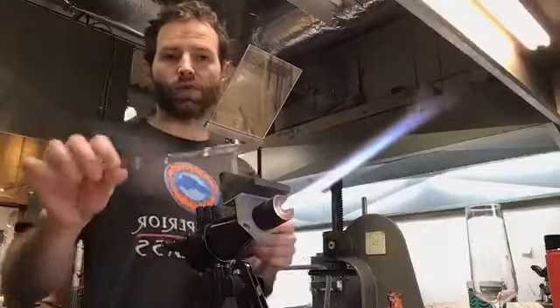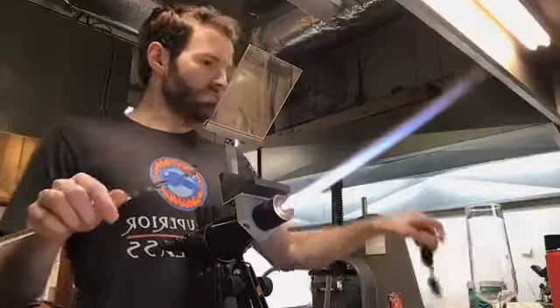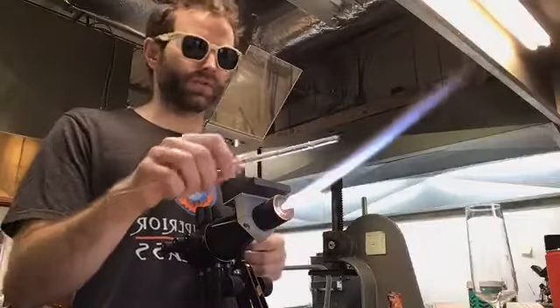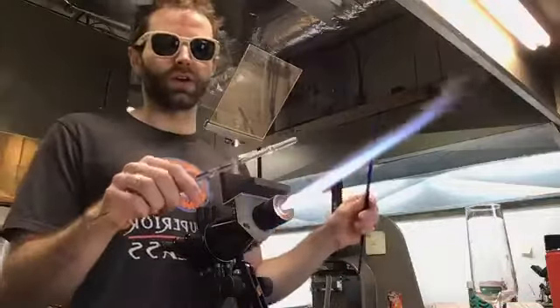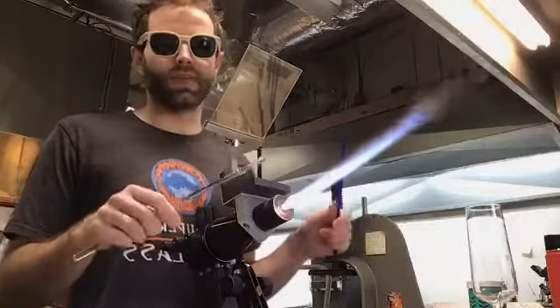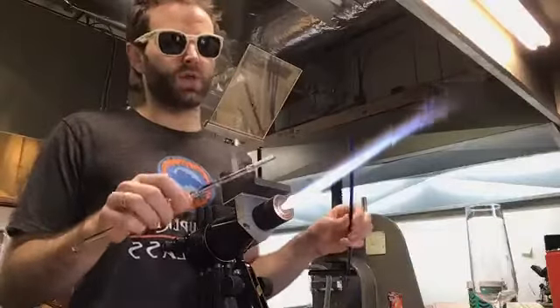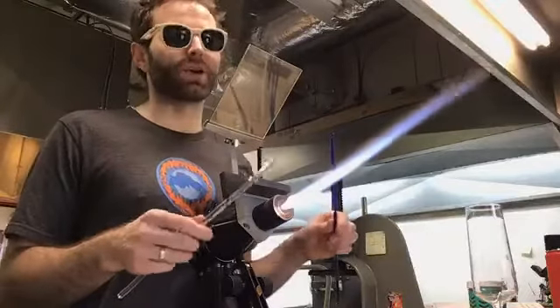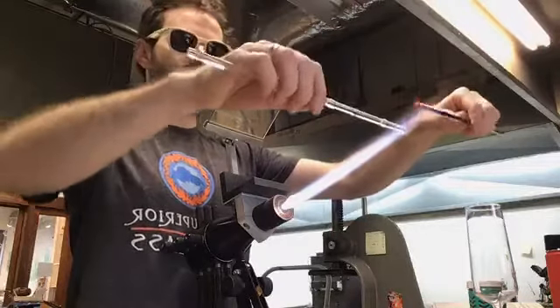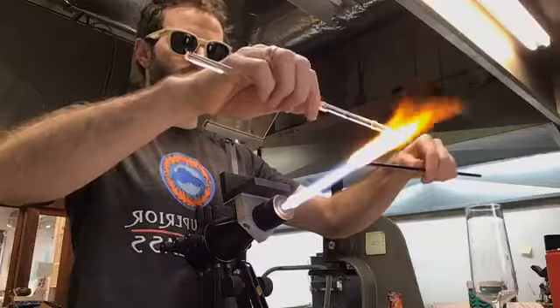We like to start with the clear glass in your non-dominant hand and the colored glass in your dominant hand — it's a little easier to control that way. Always wear our specialized glassblowing glasses that filter out the bright orange flame. I'm going to start with my darkest color first — that cobalt blue — just so I can tell how much gets mixed in. It's really easy to put in way too much color, and with your second and third color it's hard to tell which is which because they're all just glowing orange. Start with your darkest, and when you think you've put in almost enough, it probably means you've already put in plenty. We'll start near the end of the flame, letting the tips of those rods slowly warm up, then every five or ten seconds leapfrog, bringing the one from the back of the flame into the front.